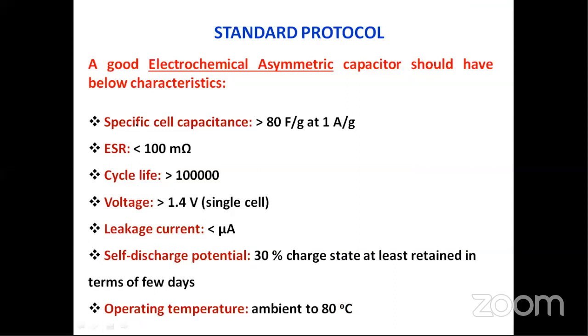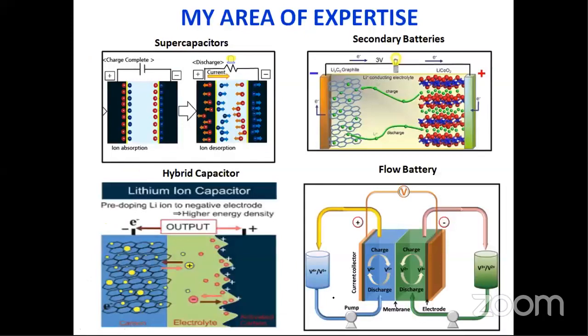And this is a standard protocol which I always use to define better capacitance and better performance of the supercapacitor. If it is in an aqueous medium, the cell capacitance should be at least 80 farad per gram at 1 ampere per gram. The ESR should always be less than 100 milliohm. Cycle life at least 100,000 cycles, or I always try to get 1 lakh cycles for a prototype. The cell voltage should be at least 1.4 volt for a single cell. And leakage current, if possible, less than a microampere is also fine. Self discharge should be around 30% even after a few days. Operating temperature should be up to 80 degrees Celsius. Of course, I get good performance even up to 80 degrees Celsius.